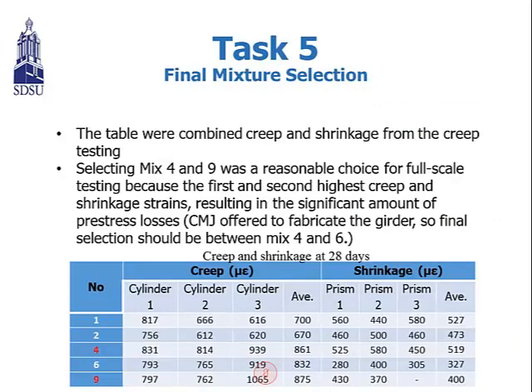And I want to talk about the reason why I chose mix 4 for the full scale testing. As I mentioned here, it has the second highest creep and shrinkage strain, resulting in a significant amount of prestress losses. When you look down the table, numbers 4 and 9 provide the highest creep and shrinkage strain. So we expect to see a significant amount of prestress losses, which is the worst scenario. That's why we chose mix 4 and mix 9.